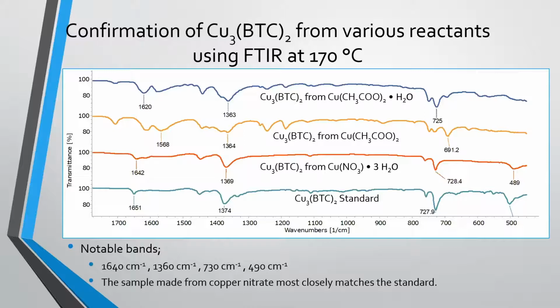This band is due to a copper oxygen bond that is present in our copper BTC. Due to water of hydration that we believe was part of our structure, this bond can be disrupted and then not appear.